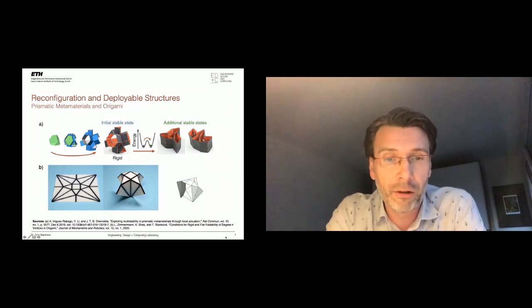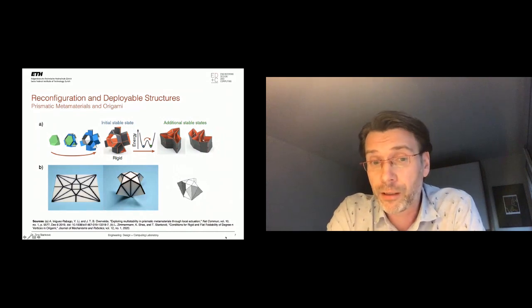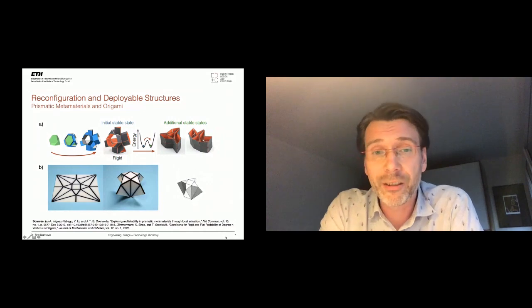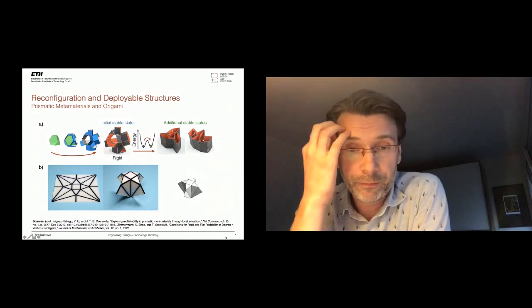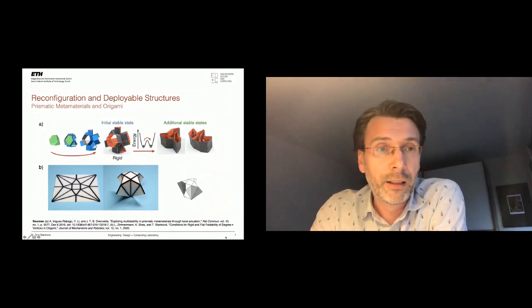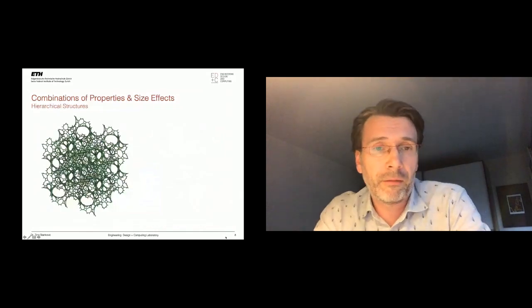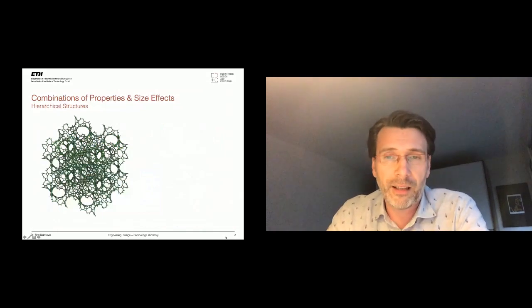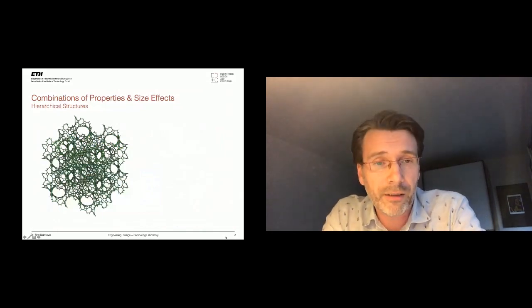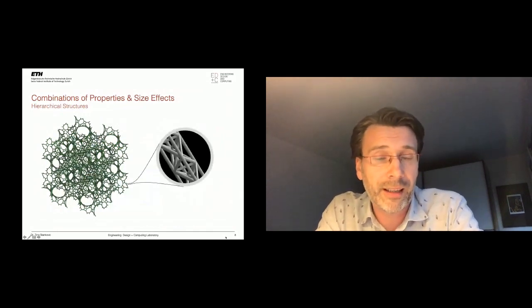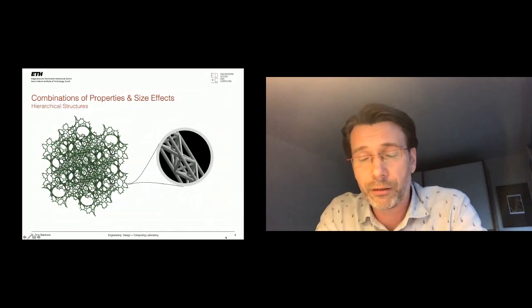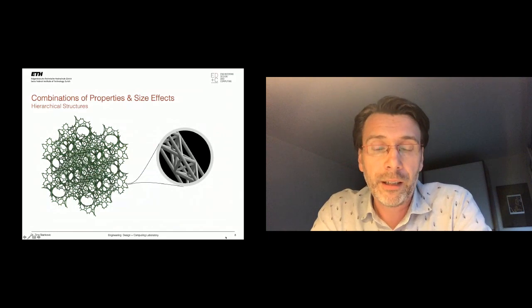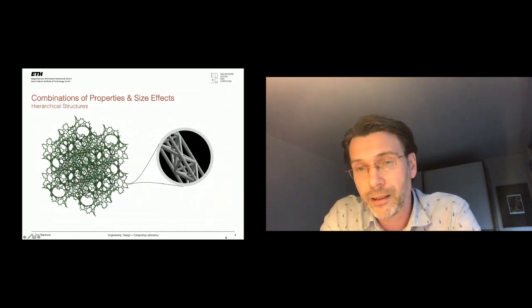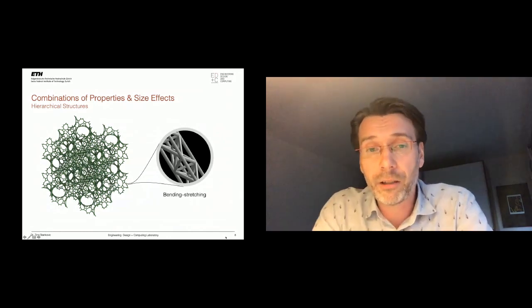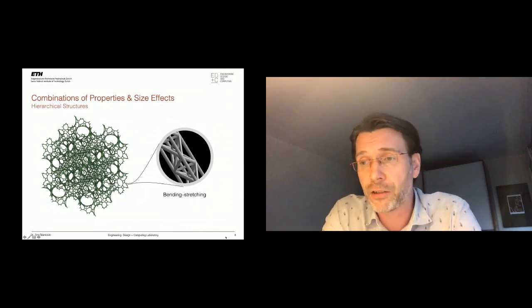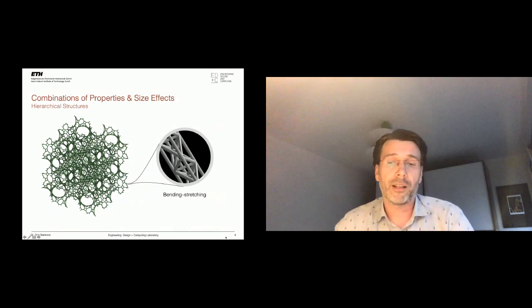This is not a metamaterial or architected material, just an example. Also, with what was discussed before, architected materials can be designed to be deployable, so that once they are inserted, they can deploy into their required state at the point of application. Of course, we have combinations of properties, and with this we usually have size effects, which I'm not going to discuss now in detail. But for hierarchical structures, each of the bars of the structure we can design further. In this example, I would have a gyroid that's bending dominated because the connectivity is less than 6, and then each of the bars of that structure would, in this particular example, be stretch dominated, and then I would have a combination of bending and stretching for the overall material. Of course, if you have stretch, then you have a structure that's high strength and high stiffness. So all of these things are possible.